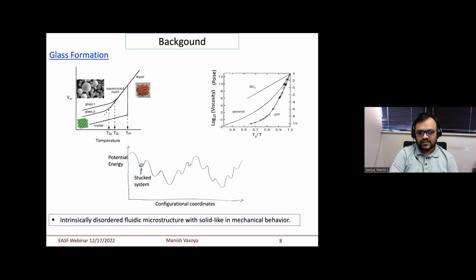So let's start with glass formation. How is this material formed? Here we have the specific volume versus temperature. If you cool from liquid very slowly, it will go into a crystalline structure, right? It will go into order. But if you cool very fast, then the liquid, instead of going into the ordered structure, will go into the disordered structure, which is the glass.